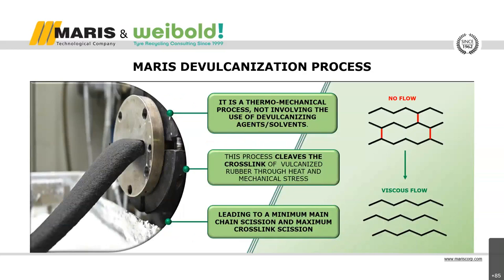The first important thing to say is that our devulcanization process is a thermo-mechanical process that doesn't involve the use of devulcanizing agents or solvents. As shown in the figure on the left, this thermo-mechanical process cleaves mainly the cross-links of vulcanized rubber through heat and mechanical stress. It is quite different from just reclaiming, because it leads to a minimum chain scission and a maximum cross-link scission. The material that originally could not flow because of the cross-links, after devulcanization, gets a viscous flow behavior.